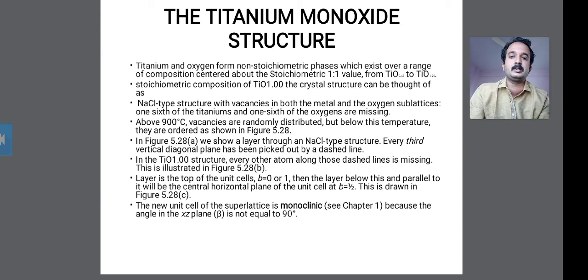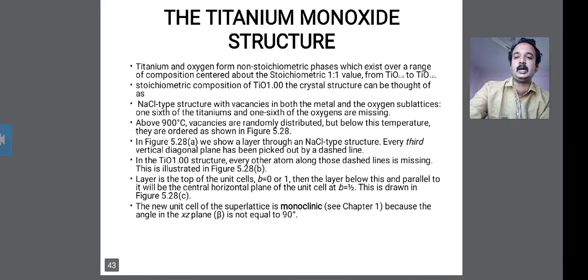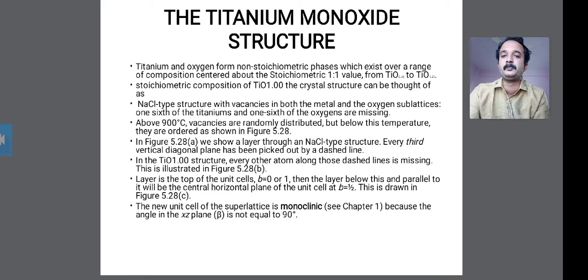Therefore, in this sodium chloride type crystal, one sixth of the titanium and one sixth of the oxygen are missing, giving vacancies in both the metal and oxygen sublattices.